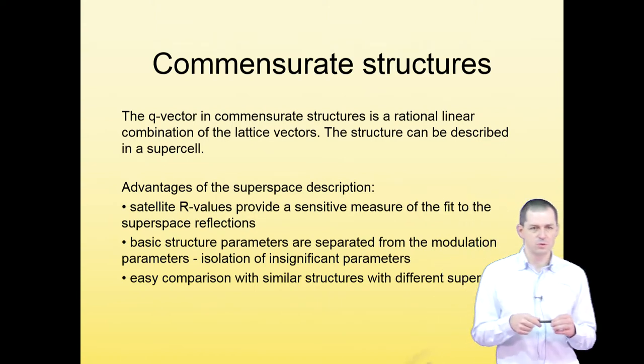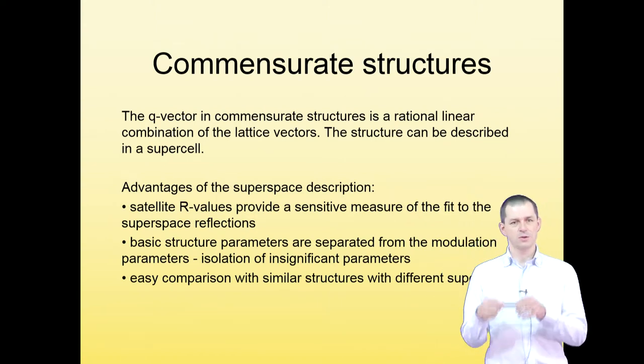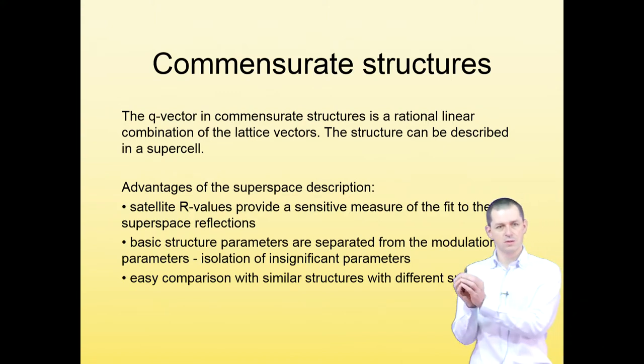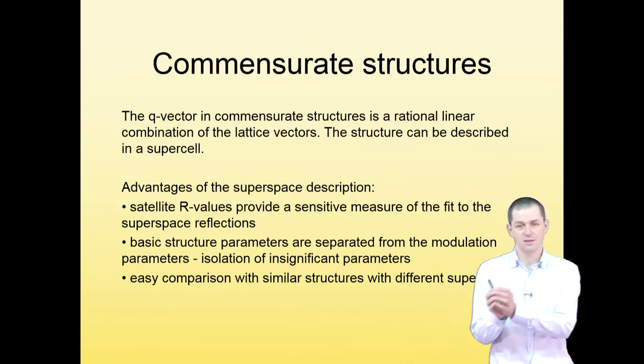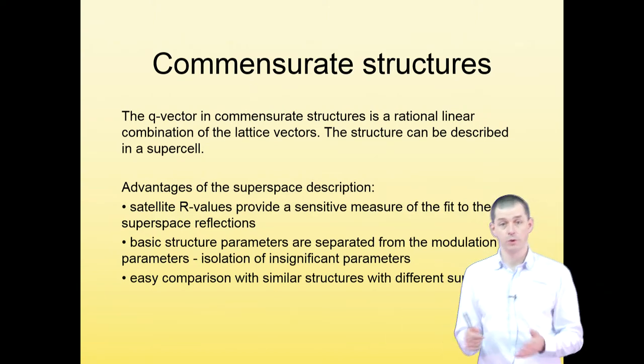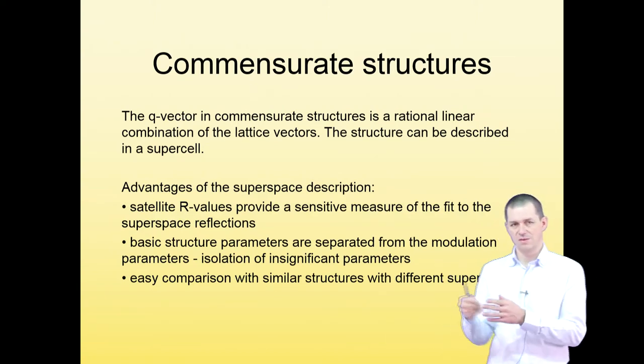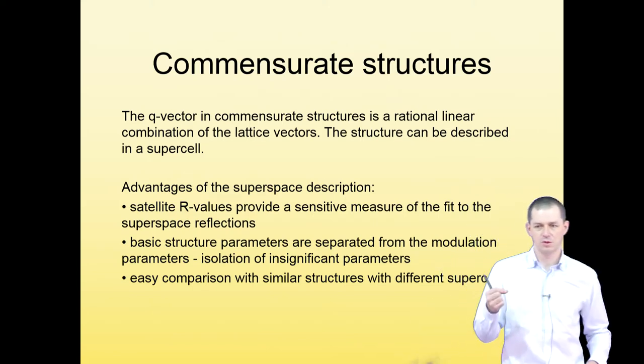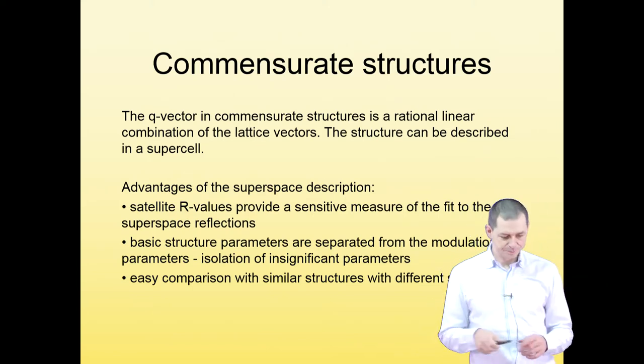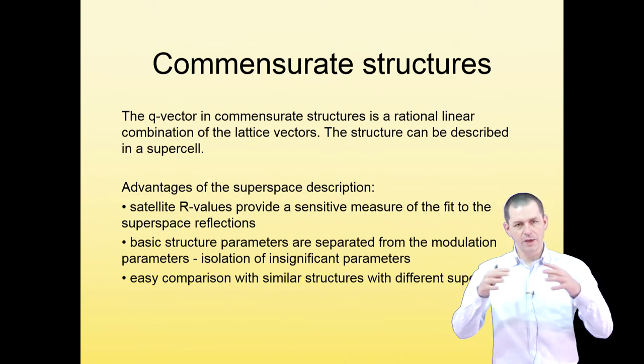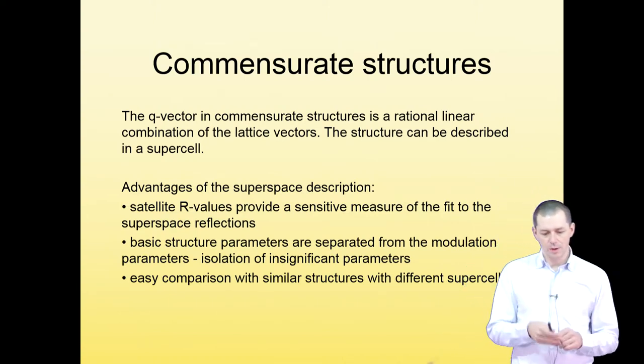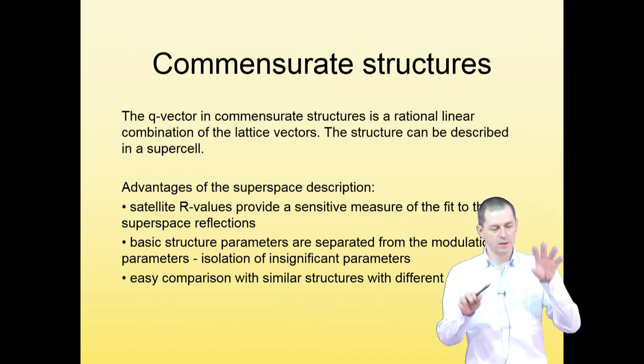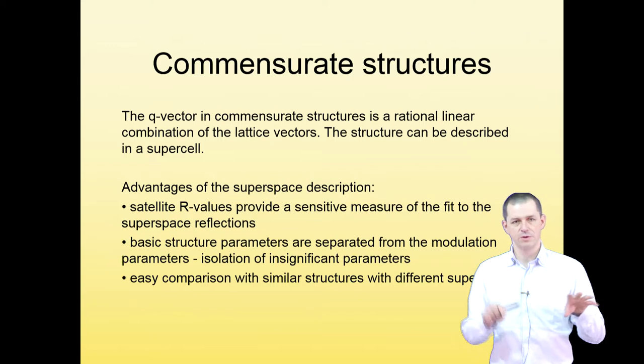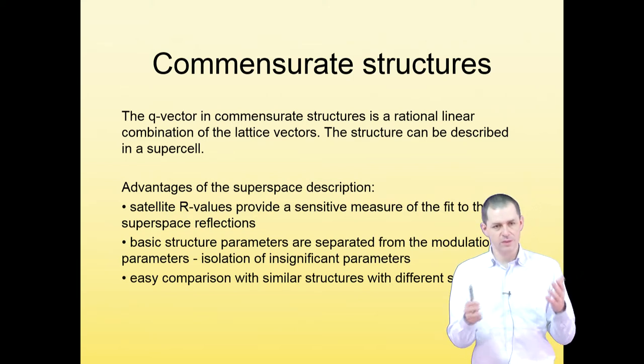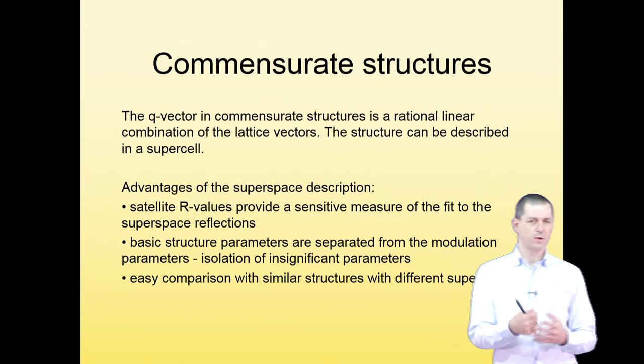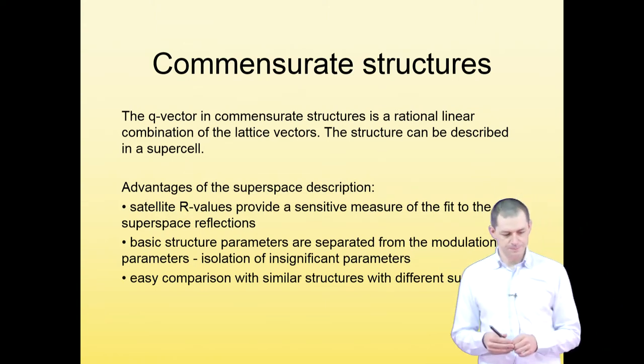you may get a very acceptable R value and seemingly good refinements, but actually you may not be describing the supercell or the superstructure properly. And if you separate only the superstructure reflections, the satellites, and calculate an R value, you may get an R value of 40%, meaning that you really did not capture the essential of the supercell, or of the modification of the structure from its average structure. Well, if you do it in superspace, you get separate R values on main reflections, separate R values on satellites, and you can see, okay, my satellites have an R value of 8%, I'm fine.